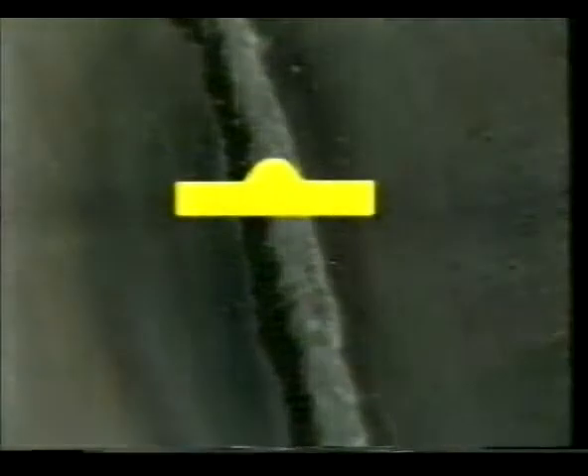The brown deposit that we can see on there is oxide, and that's due to chemical reaction. But your bead of weld should be straight and even. Now if you want to check on your welding technique, the easiest thing is to saw through at this point. And the shape of your bead should be nice and smooth with the edges melded into the metal, if you've got everything perfect.